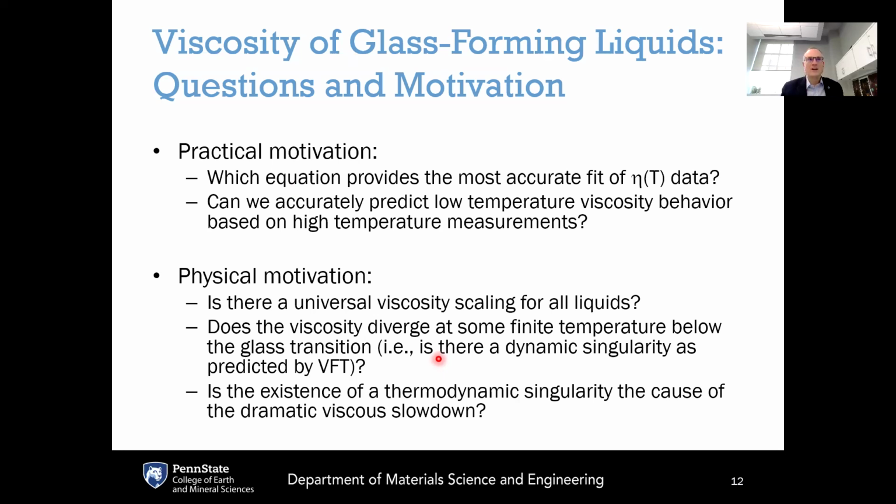Believe it or not, this actually had been debated in the literature for many decades, even though I'd argue that it's quite obviously unphysical to have an infinite viscosity at a non-zero temperature, because even if there's a small probability of making a transition, a small probability is still not an infinite viscosity. It only becomes infinite, of course, in the limit of absolute zero temperature.